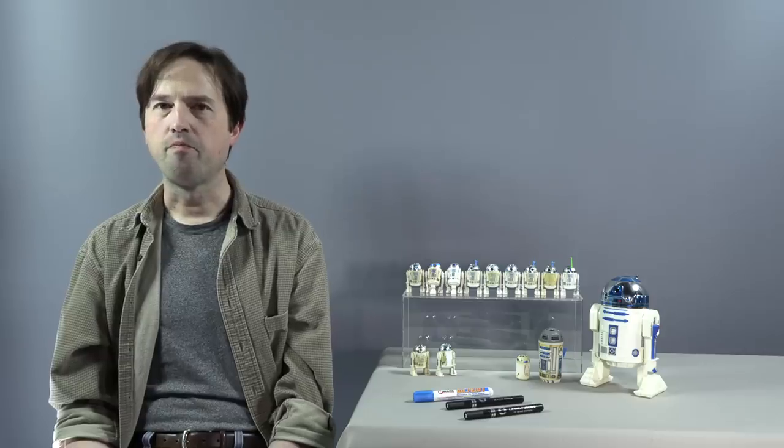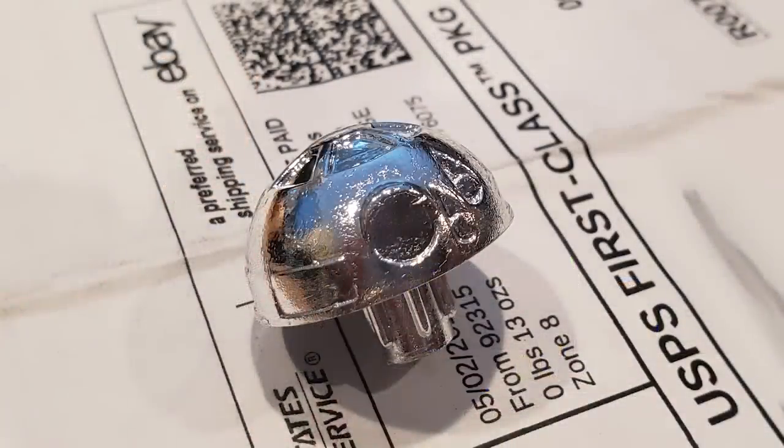I looked at it, and the dome was vac-metallized but looked rough. It seemed like either the vac-metallizing coating wasn't thick enough, or there was significant surface damage on the plastic that was now magnified by the vac-metallizing.